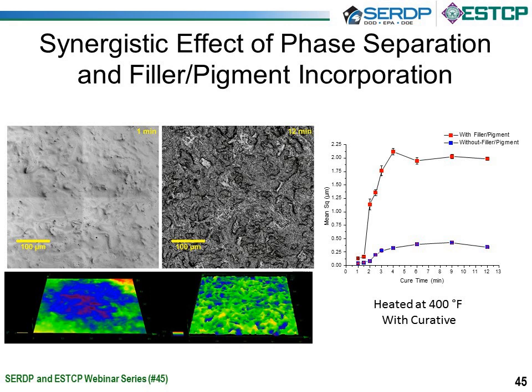And you see a dramatic enhancement of roughness with the addition of the pigments and fillers, and this rapid variation from the coatings without the pigments and filler really is illustrated at the 2-minute cure process, and typically maxes out at about 4 minutes into the cure process. And although it does decrease slightly in roughness after the 4 minutes, again, this is a necessary evil to sacrifice slight roughness of the texture of the surface interface in order to achieve a very cross-linked durable system, which is essential for the chemical resistance.